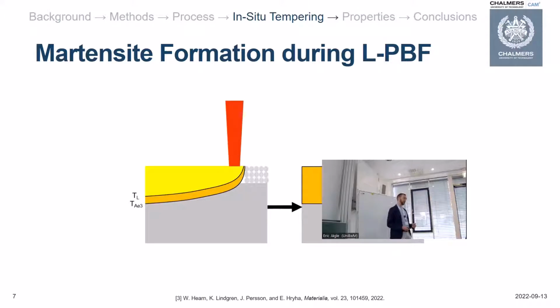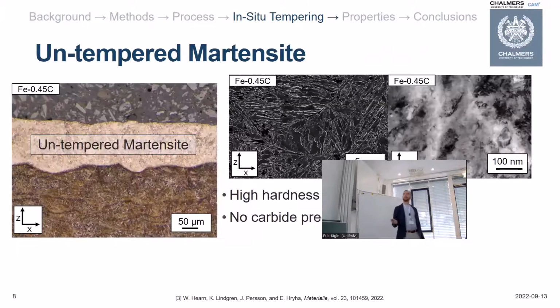And while I don't have operando results to show you, it's actually quite easy to see this untempered martensite even with postmortem analysis. You can do this by just looking at the top layer, because this layer is not reheated during the process. Looking at this iron 0.45 carbon alloy, you can very clearly delineate this portion of material from the rest after etching, as it comes out as a white layer. Then when you start doing hardness measurements here, you see that it has a very high hardness of about 750 to 800 HV, which is what you would expect in a quenched material of this composition.